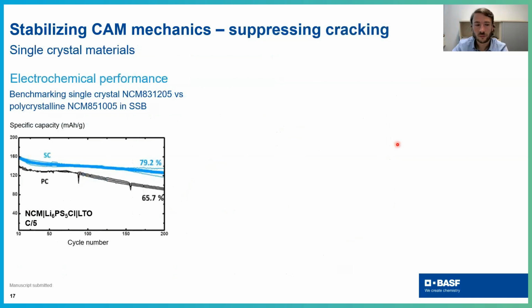Another thing, if you think about the mechanics, you can use polycrystalline or single crystalline materials. And here is a study where you compare similar chemistries of 83% nickel and 85% nickel, and you compare the behavior of these materials, which are both uncoated, in a typical solid state battery. Then you see very interesting things. First, the single crystal material delivers much higher capacity than the polycrystalline material, which is actually untypical in lithium-ion batteries with liquid electrolyte; there it is the other way around. And you're also getting better capacity retention.